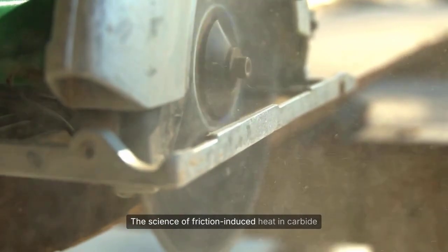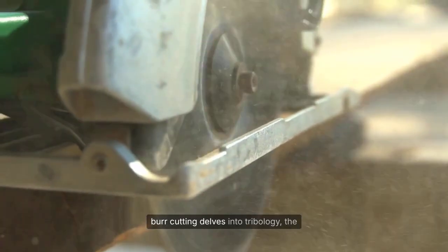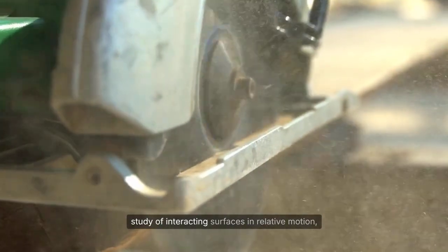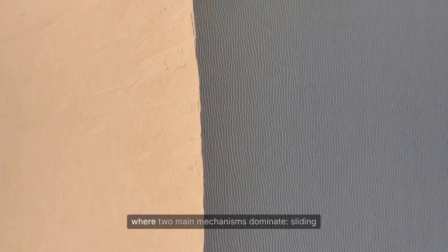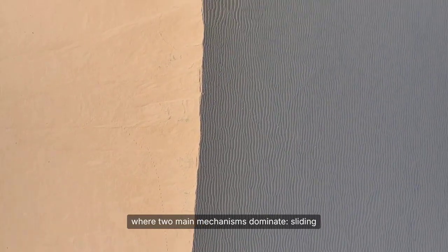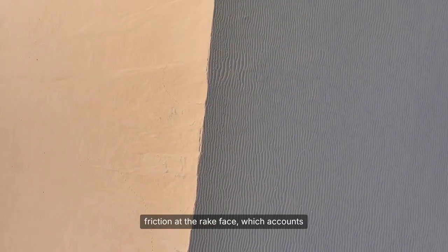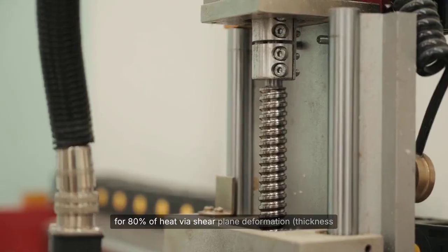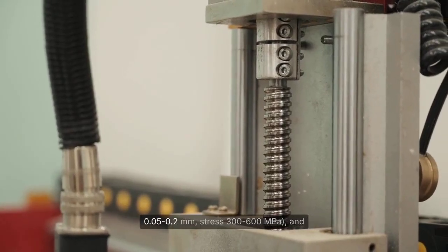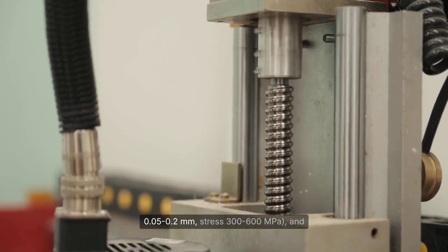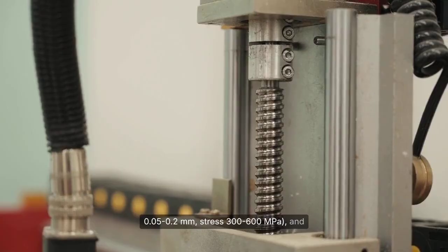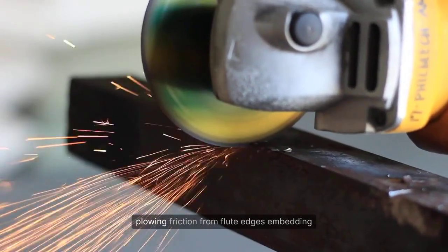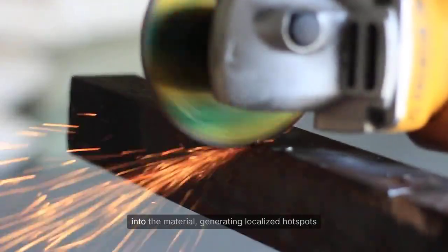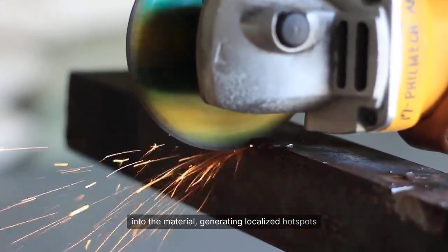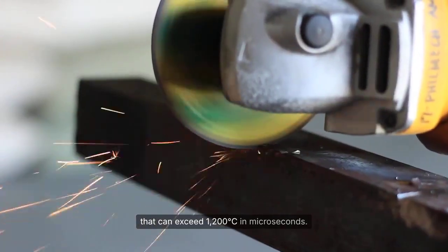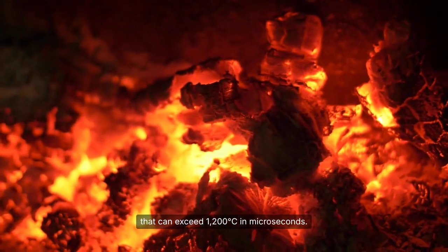The science of friction-induced heat in carbide burr cutting delves into tribology, the study of interacting surfaces in relative motion, where two main mechanisms dominate: sliding friction at the rake face, which accounts for 80% of heat via shear plane deformation, thickness 0.05 to 0.2 millimeters, stress 300 to 600 megapascals, and plowing friction from flute edges embedding into the material, generating localized hotspots that can exceed 1,200 degrees Celsius in microseconds.